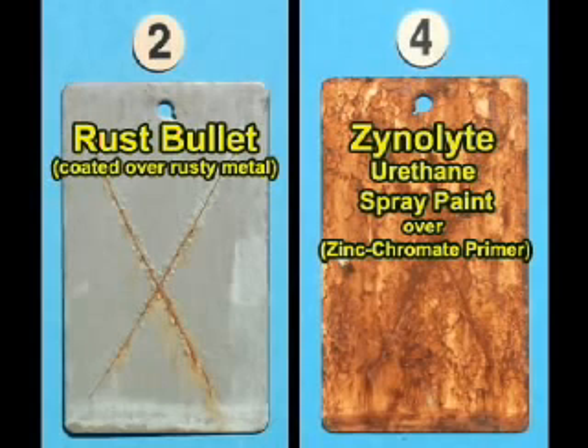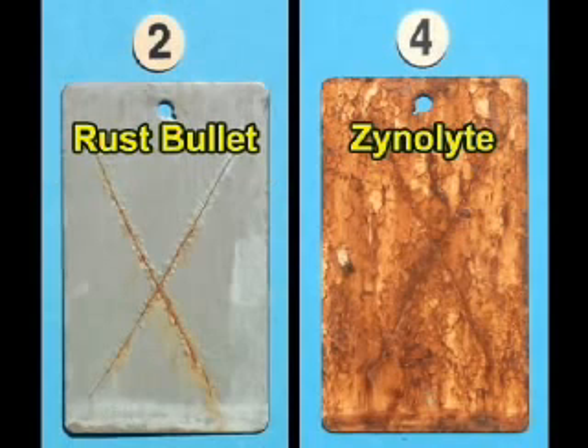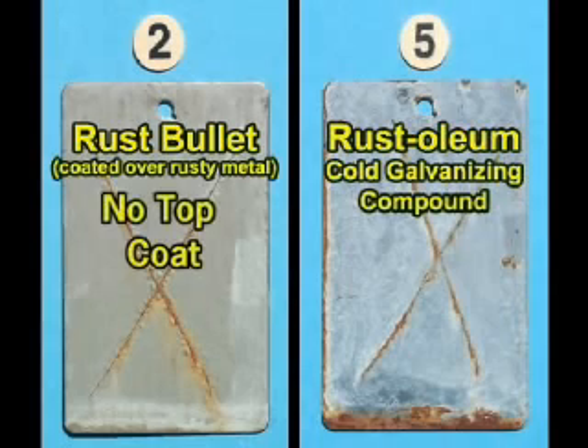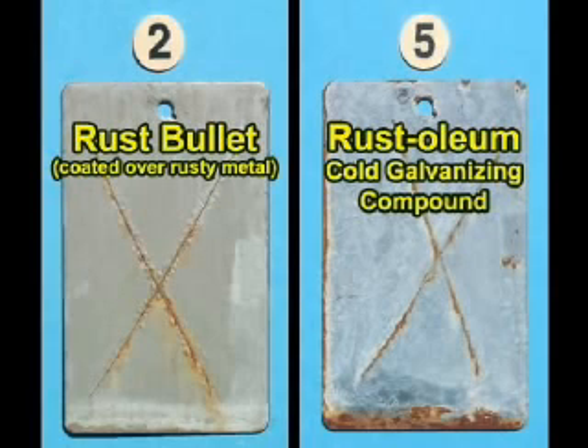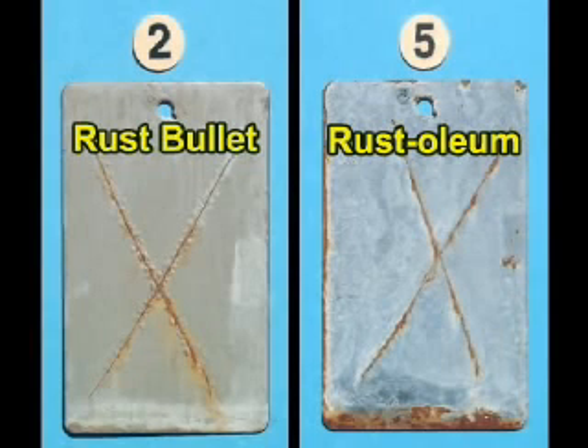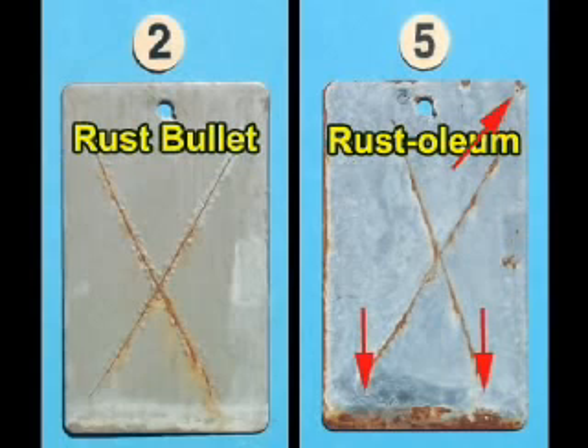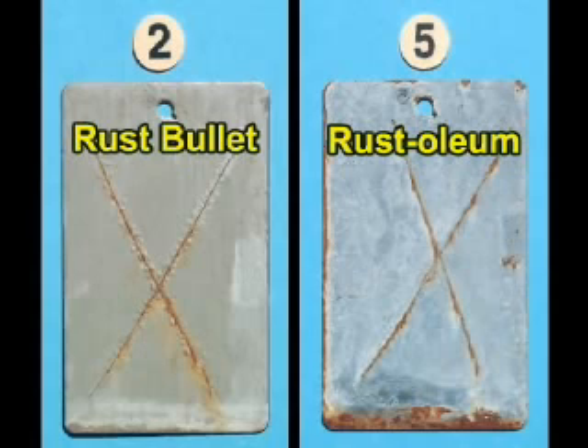This panel has Zynolyte urethane spray paint over a zinc chromate primer. Now this one is a hard one to call. The zinc chromate primer underneath is holding up pretty well. Although the inherent quality of the zinc chromate primer prevents undercutting, the urethane top coat is experiencing an approximate 50% failure. This panel is coated with Rust-Oleum cold galvanizing compound. This does provide a higher degree of protection than the others. Zinc particles are providing a degree of galvanic protection. But as you can see by the corners and the bottom of this panel, it has almost no abrasion resistance, and the resin washout will accelerate the process of decay.